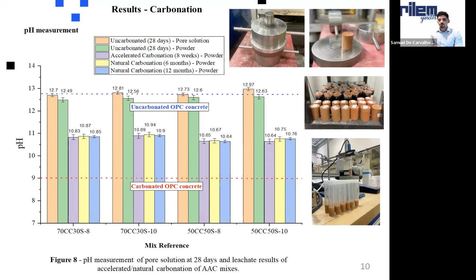pH measurement. After that, you exposed all the samples to the same conditions for the accelerated carbonation, 8 weeks. As you can see, these purple bars all show a very similar trend. After 8 weeks, we extracted the carbonated part, and it was about 10.8, 10.6 for all the mixes. Same thing for the natural carbonation after 6 months and 12 months. They have a very similar value, which was something above 10.5.